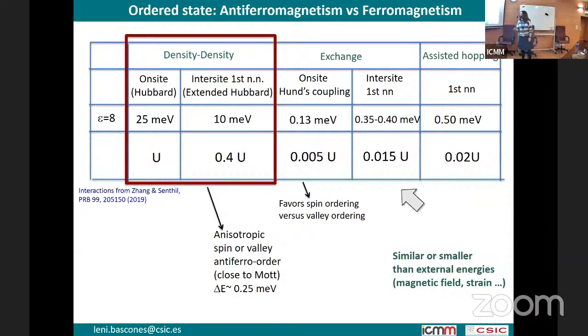Well, before I told you that these were the largest interactions, and these exchange interactions look very small, so maybe one can throw them away. But now you can see that the antiferromagnetic order that we have observed involves an energy of the order of 0.25 milli-electron volts. So somehow this is comparable to the terms that we have thrown away. Of course, here one does not have the accuracy to say whether this exchange is 0.3, 0.4, or 0.1. But it's of the order of these energies, and it can be perfectly possible that in the experiment, this exchange between the electrons at different sites really wins.